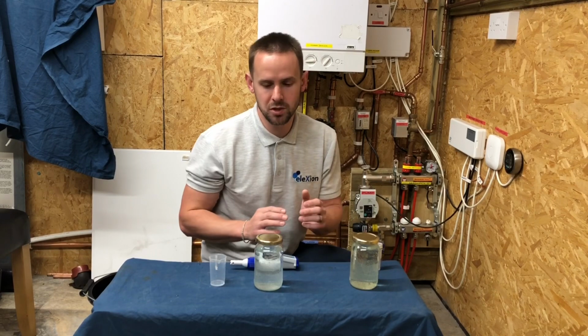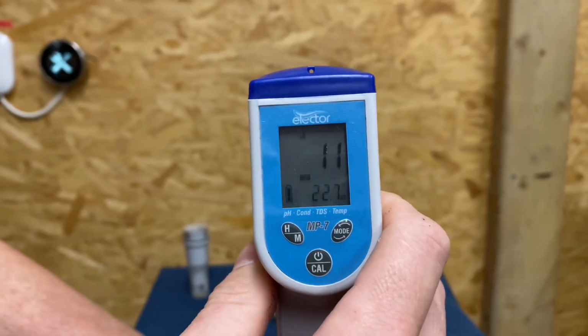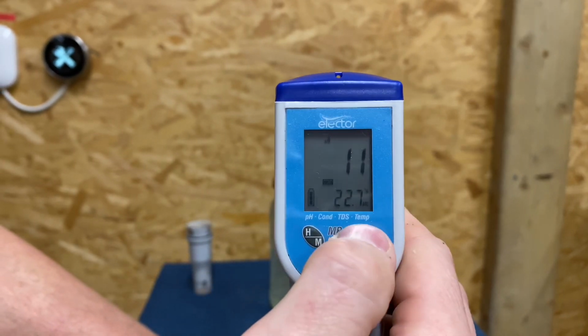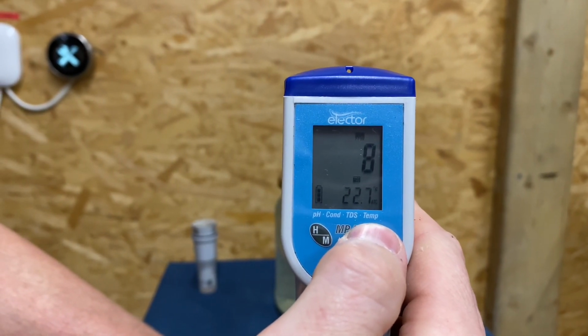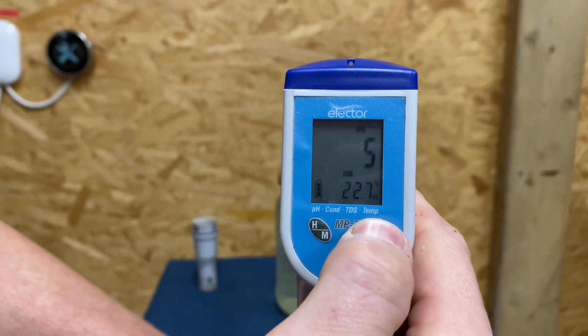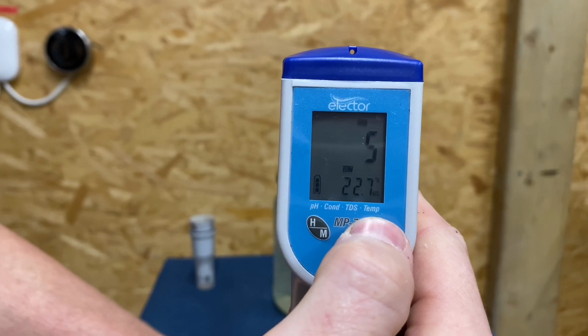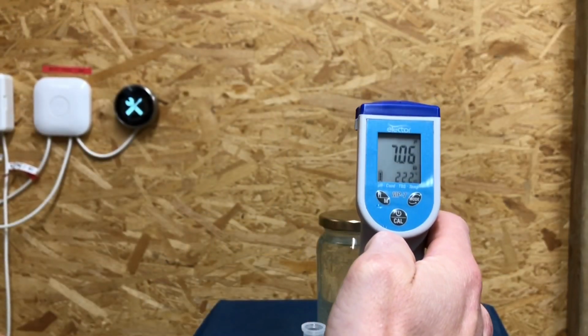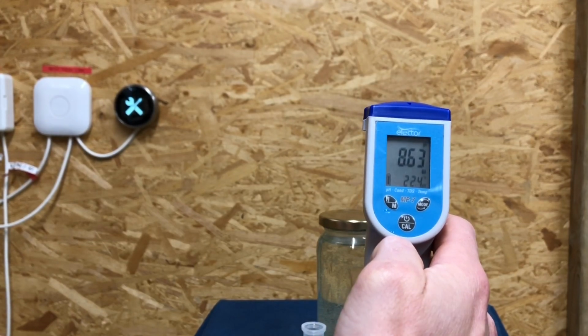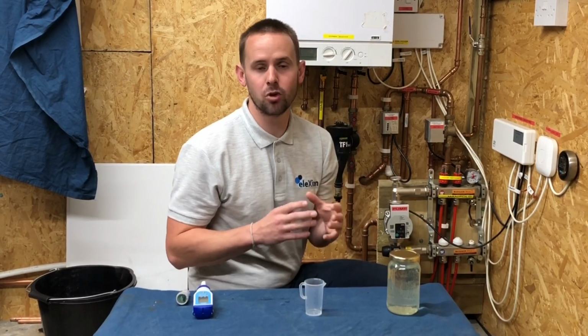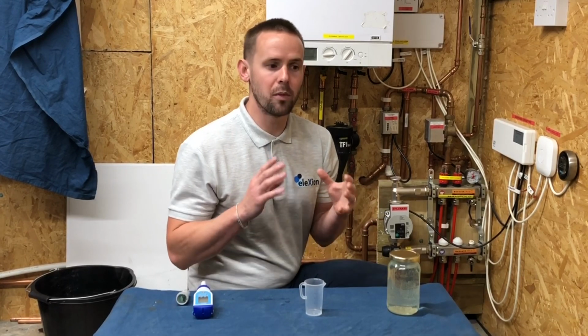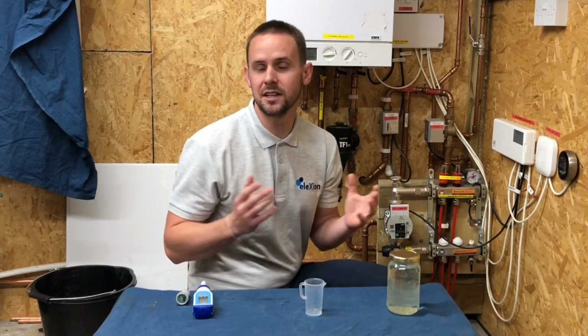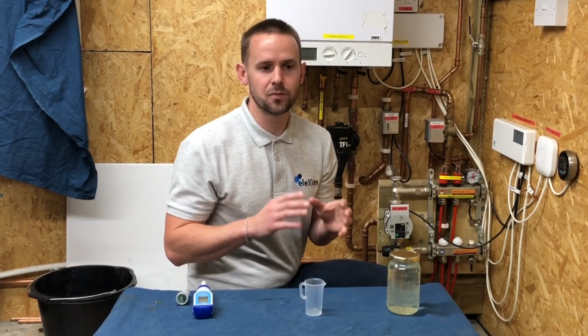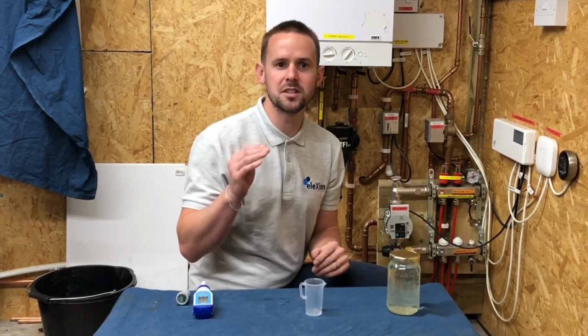So now I'm going to test the Clarimax water. Our conductivity here is 11 microsiemens. Our TDS has dropped to 7, 8. And our salts have dropped to 5 parts per million. So this is the water from the Clarimax. Change the probe over, we're just going to do the pH on the Clarimax. It's about 8.6. That little test shows that the water that comes out of the Clarimax is already ideal for our heating systems. So when we're filling with the Clarimax, we know we're going to leave the system as we intend it to be. When filling the system, you want the system not 100% demineralised, you want a little bit of conductivity in there, so above 10, but certainly less than 100.